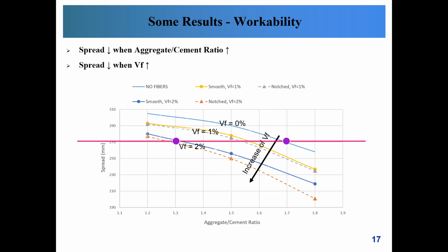For example, if you like to achieve a spread of 270 mm, measured with the flow cone here, then an aggregate-to-cement ratio of 1.7 can be used without fibers. But if you want to add 2 volume percent of fibers, then the aggregate-to-cement ratio should be limited to 1.3 and thus still achieving the same spread.